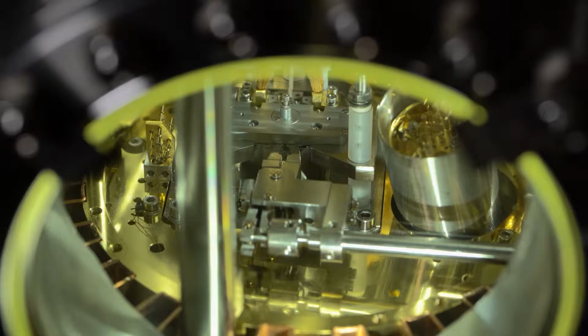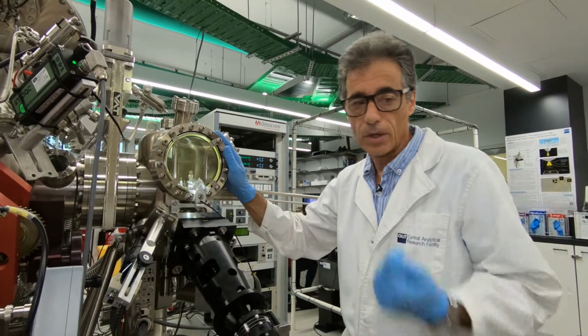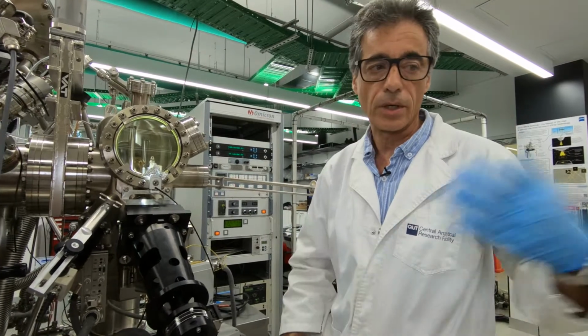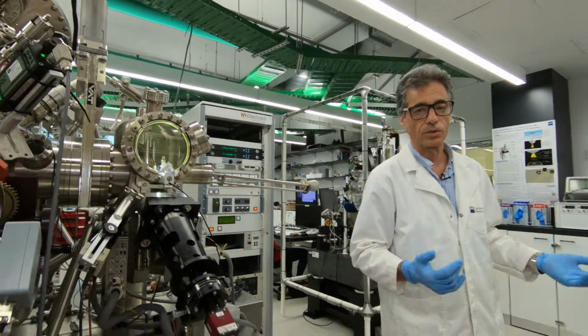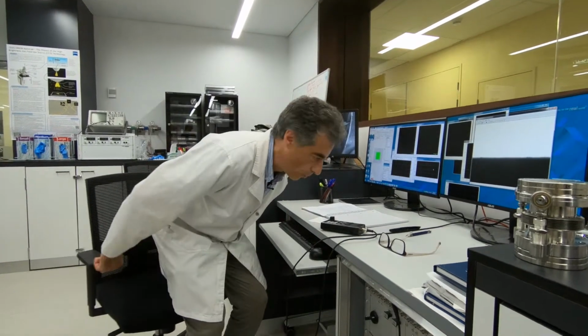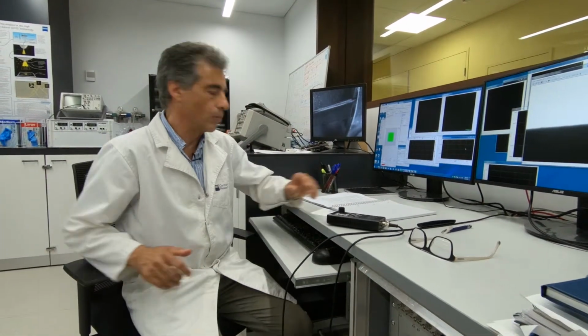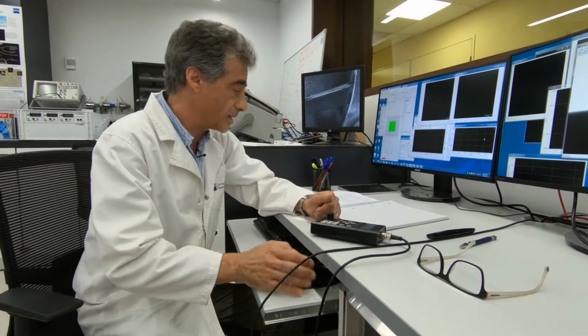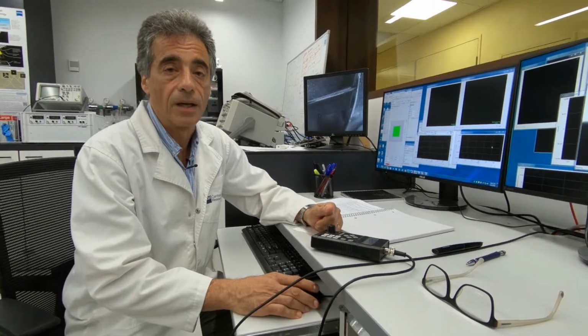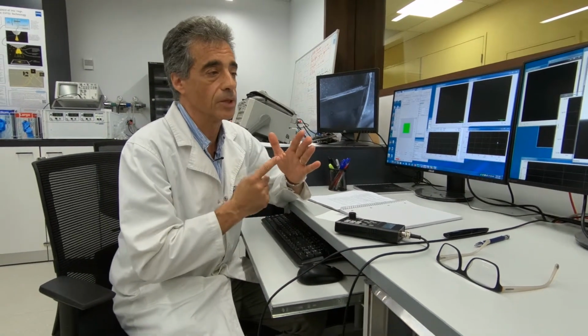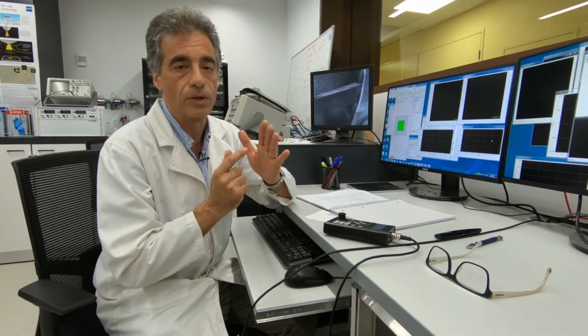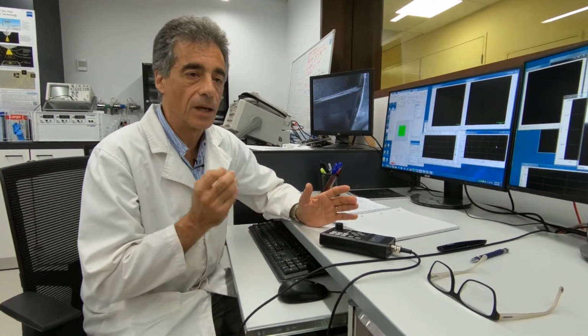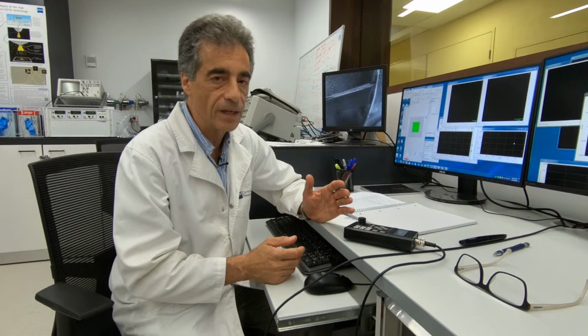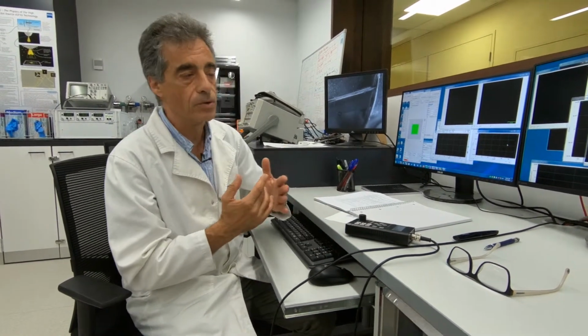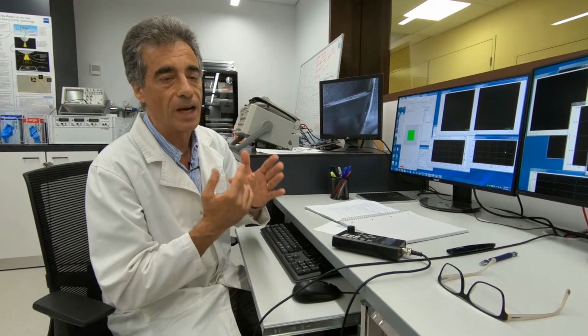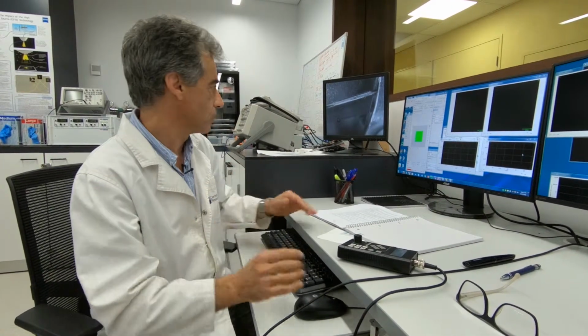Now that we have put the sample into the slot of the STM, we are going to do the measurements. So we are going to go to the computer and use it to control the STM. Okay, after we start the STM program, we can control the position of the tip. The STM is based on a quantum mechanical effect, in which we approach the tip to the surface to a very short distance, of the order of a few nanometers, and the current that is due to a quantum mechanical effect is flowing. We can control the current by using our piezoelectric system to the level of atomic resolution, so we are able to see the atoms.